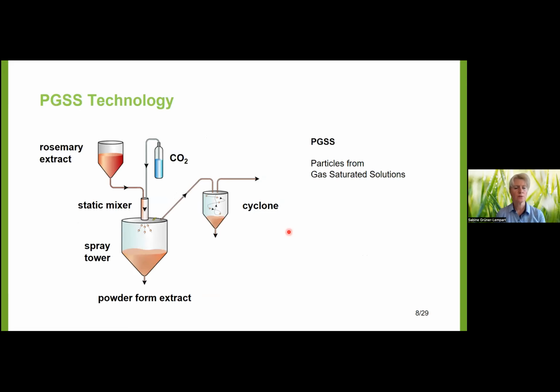You have heard about the PGSS technology today. I just want to explain it in a short way. PGSS is the abbreviation for particles from gas-saturated solutions. What we do in the PGSS technology is quite easy. We take the rosemary extract and the carbon dioxide, and both substances are fed to a static mixer to make the process continuous. In the static mixer, they are mixed intensively. Carbon dioxide is dissolved partly in the rosemary extract, and then the pressure is released rapidly to atmospheric pressure, and fine droplets are generated and finally solidified by the low temperature and by the released carbon dioxide. So at the end, we get a fine powder in the spray tower and maybe a fine dust fraction in the cyclone.